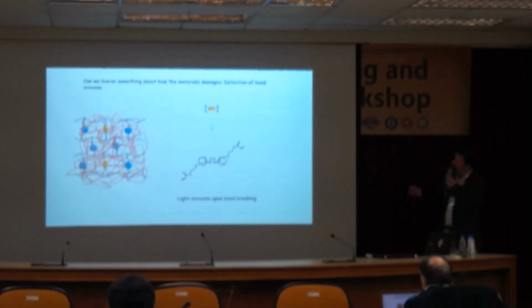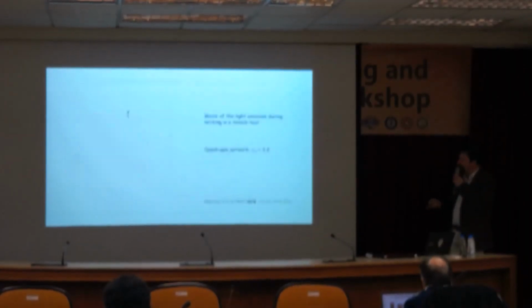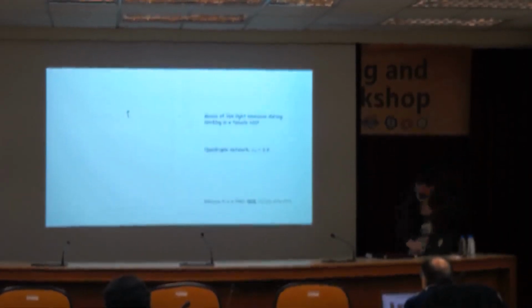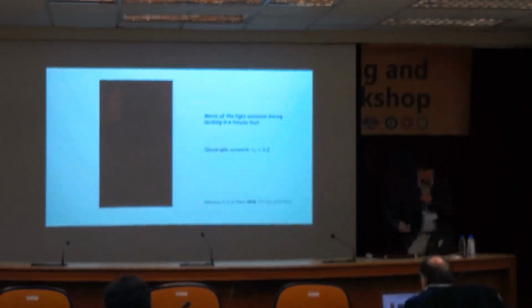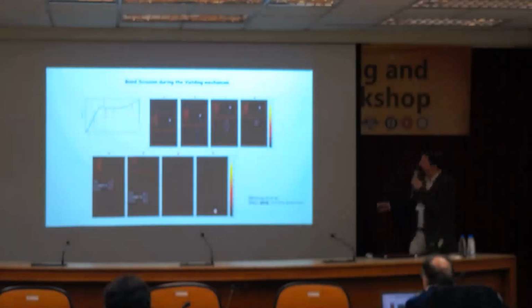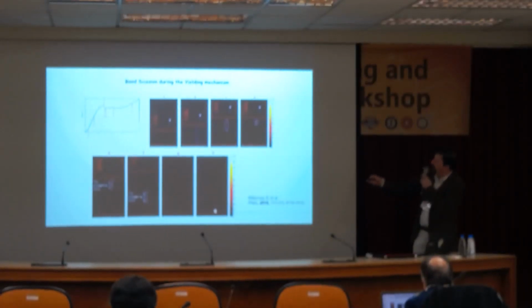So the idea there is to introduce the luminescent molecule, so the signal is not very high, but it does directly detect in real time bond breakage, so you can do it during the experiment. And here again, a little movie. I hope that there is enough contrast, but here, you don't see very much. I think the sample should be seen over here, but I'm going to go directly to the images here. So actually, during this test here, we're looking at strain and this yielding.